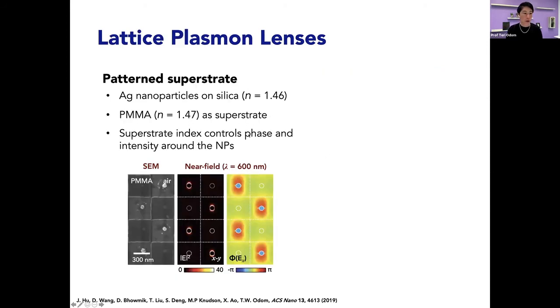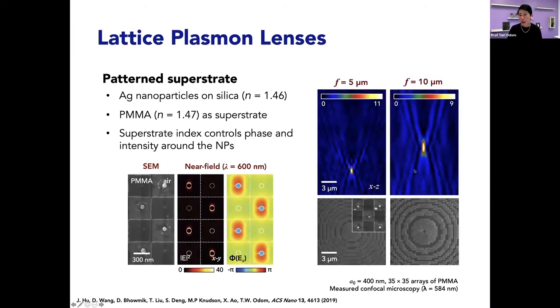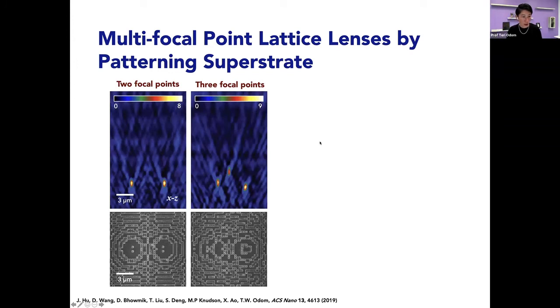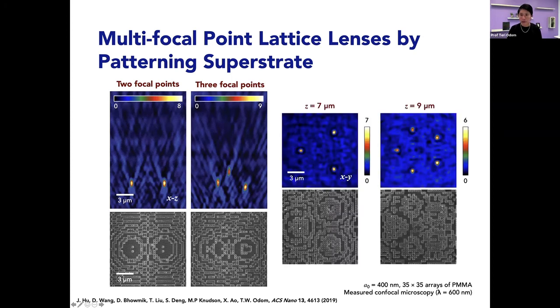And so this is the similar idea, and this is what the patterned superstrate looks like. We first started out with electron beam lithography because it was easier to pattern element by element. And you can see that it's very easy and straightforward to control the focal point. We then tried to achieve multifocal point lenses, and this is also possible. This is in the same XZ position, with different displacement in X. These are in three different locations in X, Y, and Z. And also we can control the number of focal points. Having five focal points is computationally a little bit expensive though.